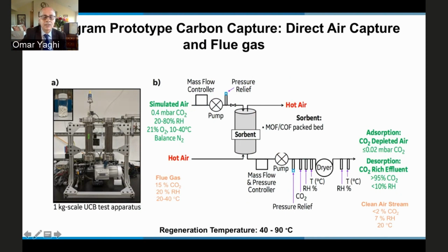And from flue gas, where let's say you start with 15% CO2, again, all of these are under practical conditions, you can get the flue gas cleaned up from CO2 down to 2% CO2. With a regeneration temperature, depending on exactly what you're doing here with the flow rates, it ranges from 40 to 90 degrees Celsius, much lower than what you would use in the aqueous amine solutions. So we're not there yet in terms of overall capacity of the MOF, but we definitely have a way to trap CO2 before it reaches the atmosphere from flue gas, and bind CO2 from air. So this is something that we are actively pursuing in collaboration with GE at this time.